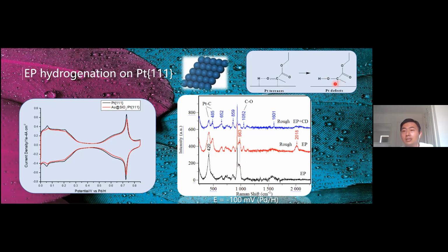So the half hydrogenated state requires a defect site on the platinum surface. And again, by adding CD, we could reduce the CO formation and increase the yield of the product.